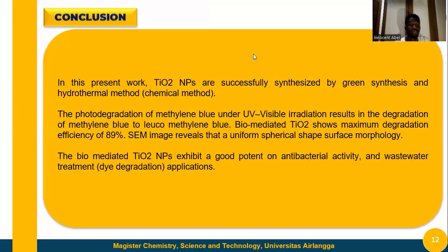So in conclusion, in this present work, titanium dioxide nanoparticles were successfully synthesized by green synthesis and the hydrothermal method. The photodegradation of methylene blue under UV-visible irradiation results in the degradation of methylene blue to leuco-methylene blue. Biomediated titanium dioxide shows maximum degradation efficiency, which is around 89%. The SEM image reveals that a uniform spherical surface morphology was available.